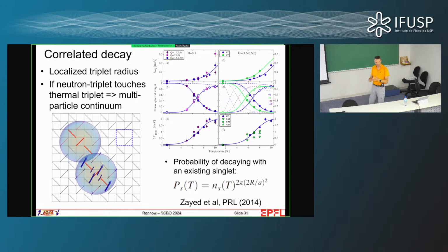We said, okay, fine, so a triplet excitation. Now, if I make a triplet on one bond, then this triplet might polarize the next spin over here and polarize. So even though the triplet formally sits on a single one of these diagonal bonds, it actually has a little bit of a finite size. Okay? Now we make the hypothesis that when we increase the temperature, there will be a very small, thermally activated population of triplets in the system. So a very low density of these, but each of them has a certain size.